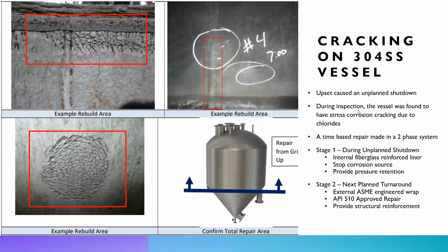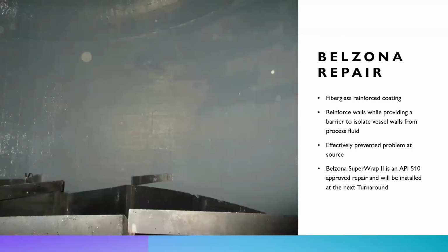So this was an upset which caused an unplanned shutdown. They were having some localized cracking around the vessel due to chlorides. It actually had a hole through, which caused the upset and the shutdown. So we were able to react fast and find a system that could handle the temperature, pressure, chemicals. And we used the same sort of system that you saw in the last example.